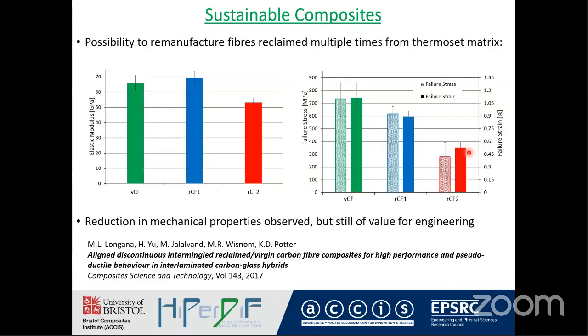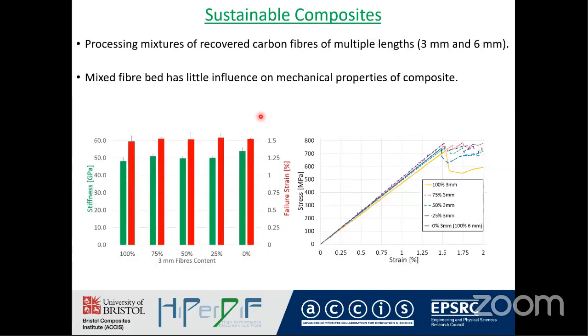So, as was described in Fraser's talk earlier in the session, the need to recycle multiple times is really key here, and Steve Pickering talked about this in his presentation yesterday. Trying to remove fibers from a thermoset matrix is very challenging, but as you can see here, the modulus and stress strain data for a thermoset material in which the virgin carbon fibers give the initial data here. You can see about 65 gigapascals. The first recycling step, in which the fibers have been removed from the matrix, replaced into another matrix and remanufactured, gives us a second life, and the potential for another recovery and recycling is also evident. So this is a very, very versatile technique.